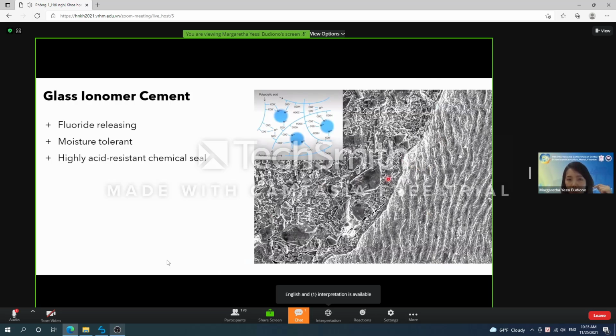So this is a microscopic image of a GIC material and the interface between GIC and enamel. So this side is GIC, this side is enamel, and this is where they meet. If you look closely, there is actually a thin line running near the surface of enamel. So sometimes when GIC material fails, it is more of a cohesive failure rather than adhesive failure. What I mean is that when it fails, the material breaks away from the cavity, but the chemical bond stays behind. And the chemical bond is this calcium polycarboxylate salts. And since this is a highly acid resistant structure, this actually forms a protective layer for the underlying tissue. So this is one of the main benefits that we can't get from composite.